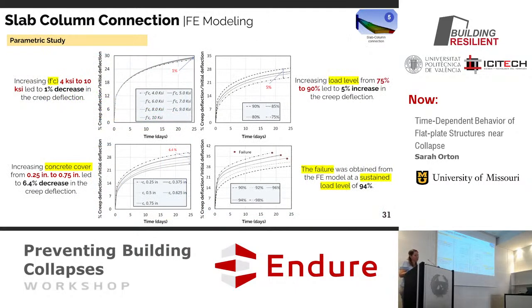Did some parametric studies to see the influence of the concrete strength, not a big influence. Increasing the load level can increase the deflection, but it's not a huge increase. Increasing the concrete cover can decrease the deflection, but it's not huge. And we saw that we would get failure if we had a load level of about 94% or above. If we had lower load levels, then it wouldn't eventually fail with time.